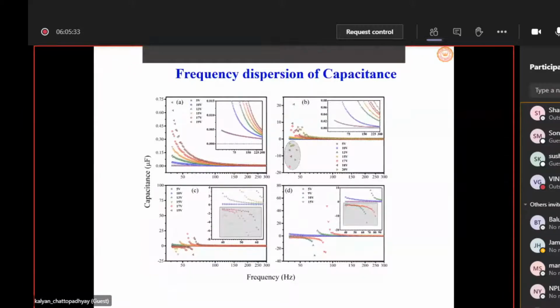But most interestingly, this result I just mentioned, you see that it is the capacitance versus frequency plot. This is for undoped zinc oxide. As usual, it is expected that this type of dispersion, capacitance versus frequency, you should expect. But what is unusual is that as soon as you incorporate doping at the anionic site, you see that there is a capacitance switching. That means negative capacitance is coming at some portion of frequency.